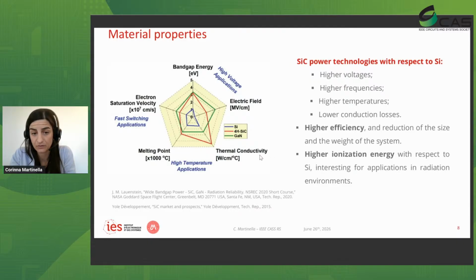Also, it has a higher thermal conductivity and a higher melting point with respect to silicon. And so this allows the use of devices manufactured in silicon carbide at higher temperatures. It has a higher electron saturation velocity with respect to silicon, and so you can switch the component faster. So overall, this technology allows applications at higher voltages, frequencies, and temperatures, and also reduces the conduction losses. So you're improving the efficiency of your system, meaning that you can manufacture something more compact, and so you're reducing the size and the weight of your systems. This becomes particularly interesting, for example, when you need to fly your power converter, for example, in aerospace applications.